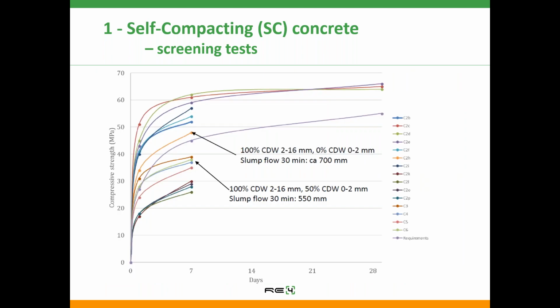So a graph showing the compressive strength versus the age. They were tested up till 7 days, just as I said, to see the effect that the recycled demolition aggregate was going to have on the compressive strength. The ones showing 28-day strength are the ones with the newly quarried aggregates, and you can see that strengths above 60 megapascal were being obtained. But once we started replacing 100% of the newly quarried aggregate with recycled aggregate, then the strength dropped to slightly below 50 megapascal at 7 days and dropped to below 40 megapascal when both fine and coarse aggregate were used.